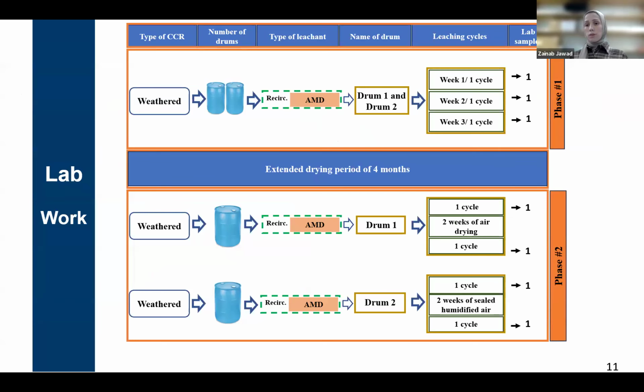Then we decided to scale the size of the testing. So we went from columns to drums, size 55-gallon drums. That was done to eliminate any possibilities of preferential pathways that the leaching solution might follow due to the small size of the column. So we used the weathered refuse with AMD as the leaching solution based on the results of the column testing.